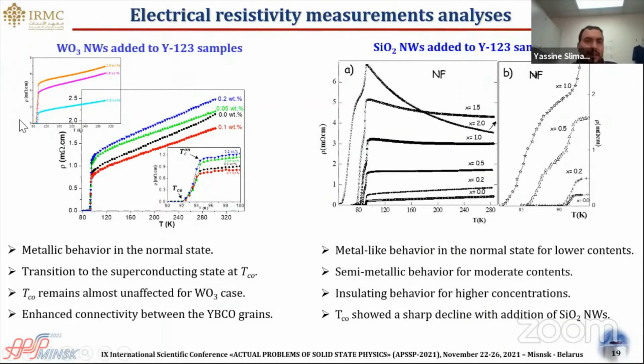We presented here the electrical resistivity measurements versus temperature for YBCO samples added with different amounts of nanostructural materials having different behaviors: semiconductor for the case of tungsten oxide, and insulator for the case of silicon oxide.